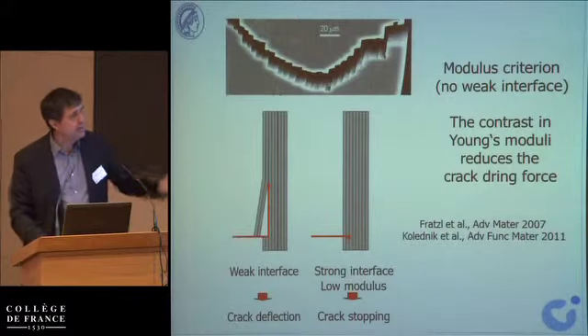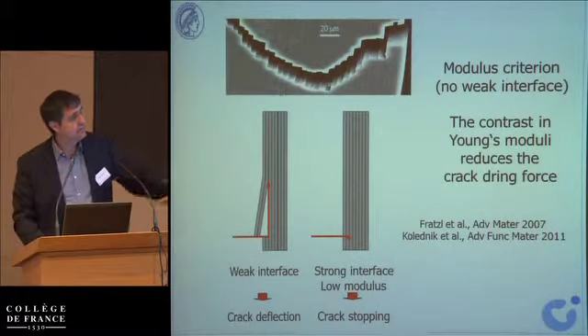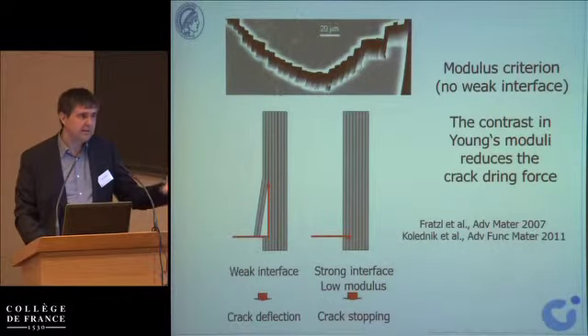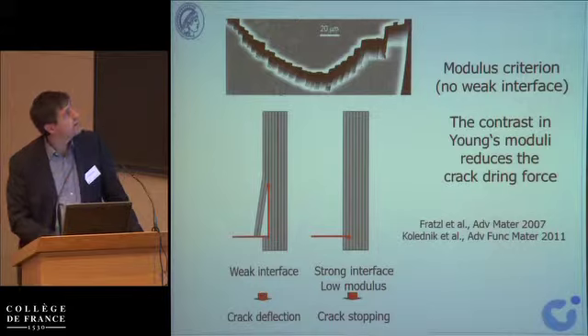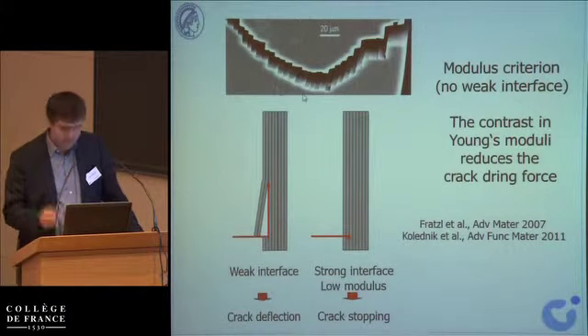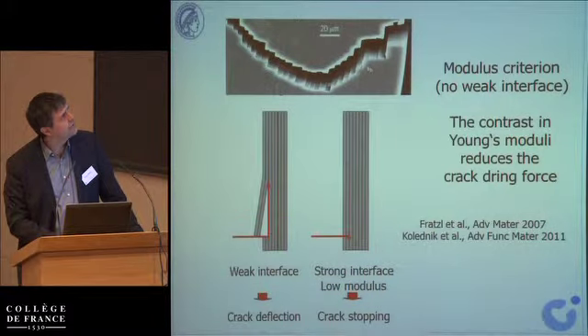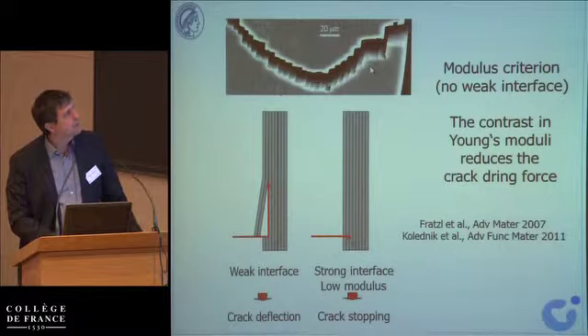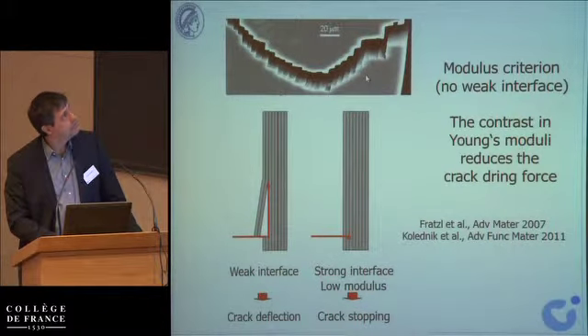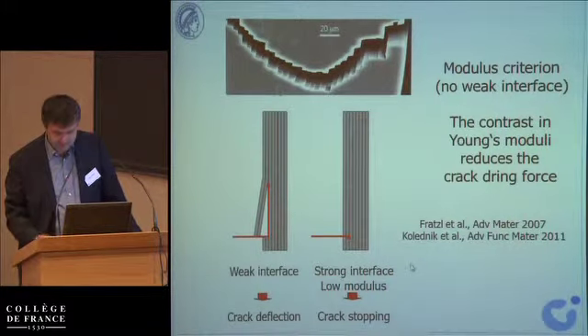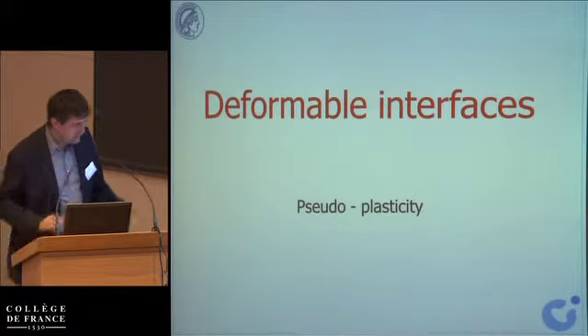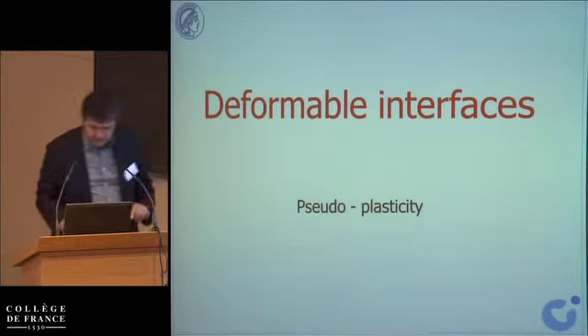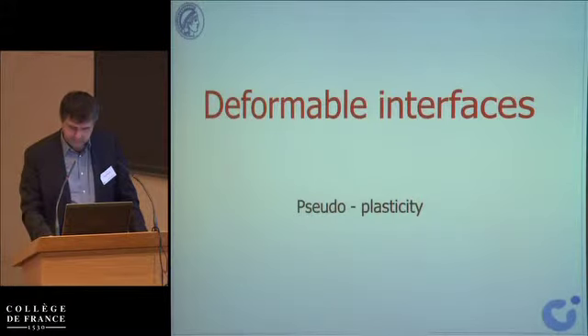And this can be generalized to materials that have periodically varying stiffness, such as, for example, in these glass multi-layers or any other multi-layers. It turns out you need a minimum contrast, like 5 or so, to really get a good effect. But with a contrast of 5 in terms of elastic modulus between the layers and the layers in between, you get a very, very strong reduction in the driving force of cracks across this multi-layer. That's explained in these papers here. So separating materials into pieces is dramatically reducing the fragility.